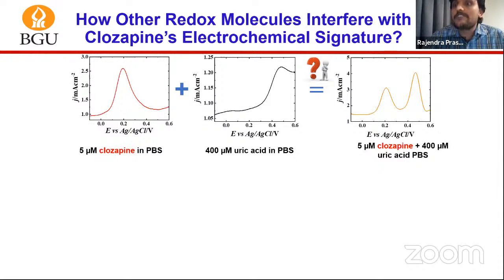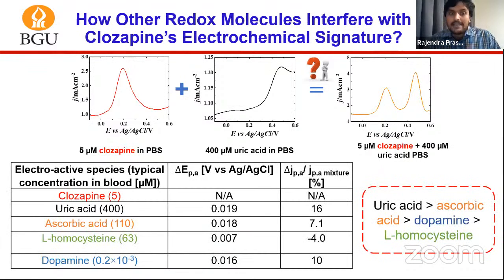This slide shows you the effect of interfering species. We characterized the interference magnitude by recording the differential pulse voltammogram and calculating the shift in the peak potential and percentage change in the current density. What we did basically, we recorded the differential pulse voltammogram alone of these molecules and then mixed these molecules with different interfering species with clozapine. Here you can see with uric acid the shift is highest, and also the percentage change in the current density is highest, meaning that this is the major interfering species which is going to affect the clozapine signature in the measurement.